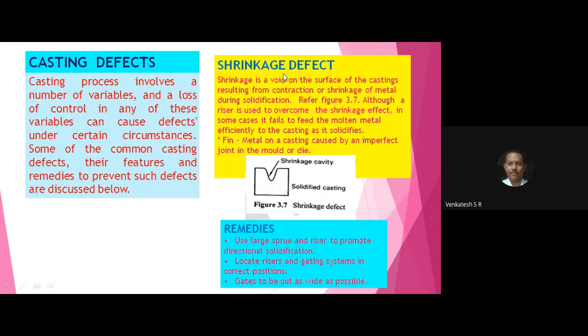Shrinkage means a shortage of liquid metal in the mold, so that there will be a hole, void or cavity in the metal. This type of defect can be removed by using a riser, a blind riser, a special type of riser, to avoid the formation of shrinkage defect in the casting. That's one method. The other method is to use excess metal. They should not allow the shrinkage of liquid metal, so that you can prevent the formation of shrinkage defect.